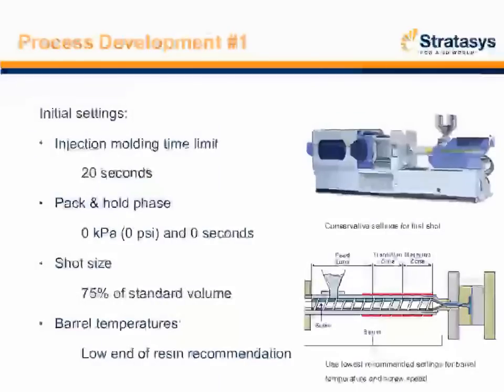So the initial settings here are setting the injection molding time limit to 20 seconds, setting the pack and hold phase to zero pressure and 0 seconds, of course, at the process development stage, setting the shot size to 75% of the standard volume, and the barrel temperature at the low end of the resin recommendation.